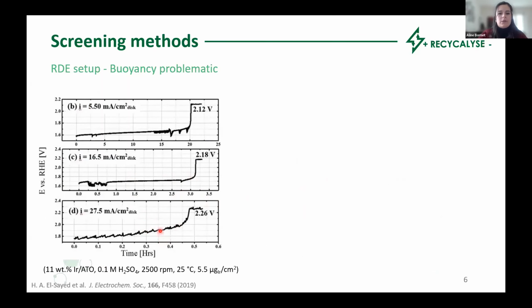In this paper, the authors applied a constant current on their iridium on ATO catalyst and recorded the potential. And as a quick reminder for you, the higher the potential at a fixed current, the worse the catalyst is. So here, if we have a closer look at the D plot, where a current of 27.5 milliamp per square centimeter was applied, we can see that the catalyst loses its activity in the course of the experiment, as higher potentials are recorded. And this was explained by a slow covering of the catalyst by bubbles.